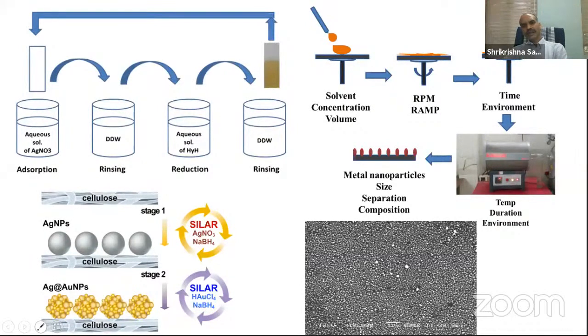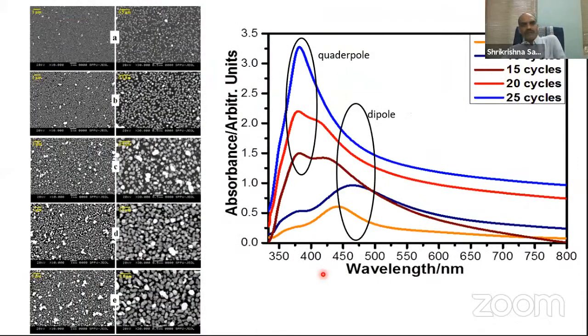Another technique we use is similar to SILAR, but here we put the metal ion solution on a substrate and then we spin coat it. When we spin coat it, we get metal salt nanoparticles, and then we reduce them either thermally or chemically, and we get uniformly distributed metal nanoparticles. You can see one typical SEM image where these metal nanoparticles are grown on a very large surface. That is also important, because we want to detect probe molecules at different spots. If they are all uniformly sized and with the same separation, I can take the signal from this point, this point, and everywhere. So the same substrate can be used for detection of very large samples.